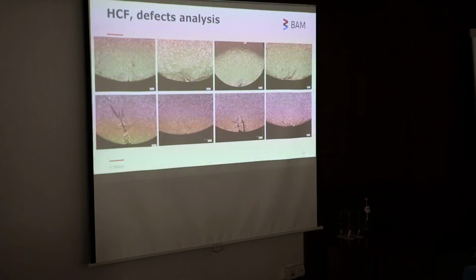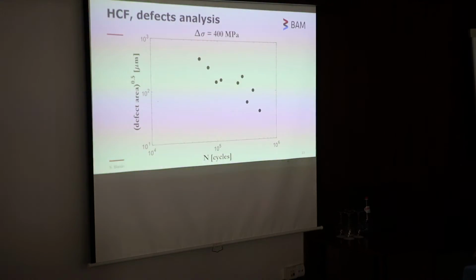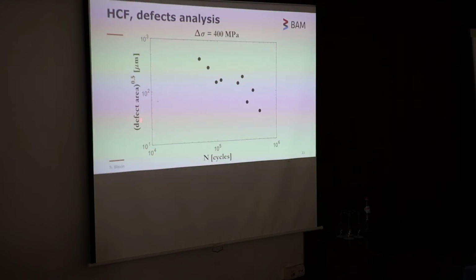And when we use, instead of the stress range versus the number of cycles, which is the typical representation for the S-N field, the defect size, in this case the square root of the defect area against the number of cycles, we can see a clear dependence of the lifetime on the defect area. This is in agreement with many results, and probably this lets us know that the short crack regime is practically nonexistent in this case, and we are always working with the propagation stage.